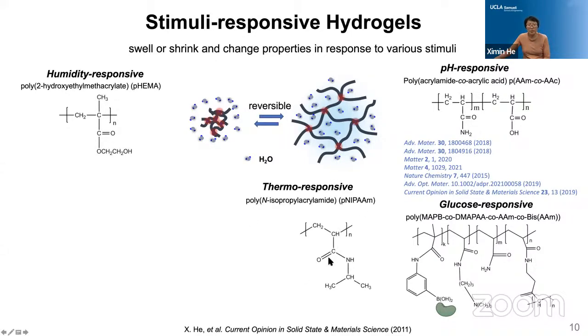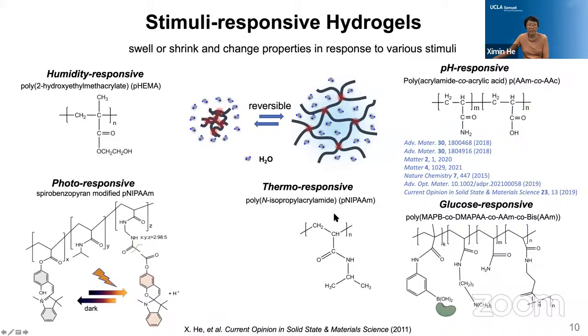And also thermal responsive hydrogel, polyNIPAM, along with some other thermal responsive polymers, have been very well studied. For example, NIPAM can shrink upon heating across 32 degrees C and re-swell when cooled down. And this critical temperature point can be tuned by several different ways, including introducing hydrophilic or hydrophobic small molecules in the precursor solution.